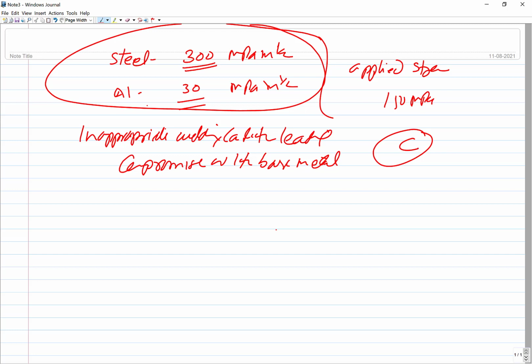I'll tell you one more thing, the fracture toughness and the simple toughness almost go together, but the significance is different. Simple toughness indicates the energy absorbed under high rate of strain loading during impact conditions, while this indicates the resistance to crack growth, which is quantified in different ways. One I have already talked about, like stress intensity factor. There can be other energy based criteria also, but fracture toughness is used to indicate the resistance to crack growth.